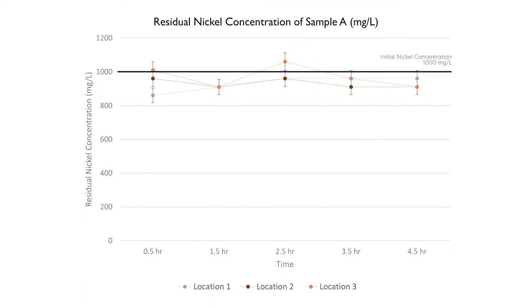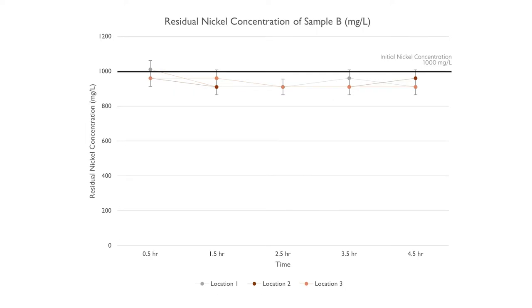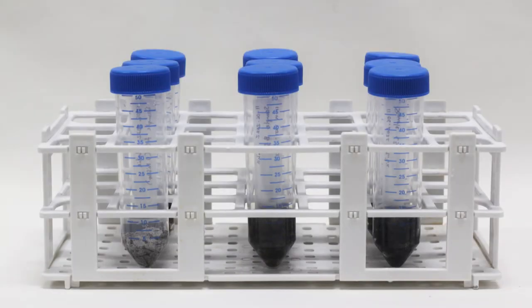Results revealed that the material-to-water ratio is significant in ensuring effective heavy metal absorption. In the water tank, too little material was used to remediate the amount of polluted water, and it was therefore ineffective. We then set up a second experiment with a higher material-to-water ratio to obtain clearer results.